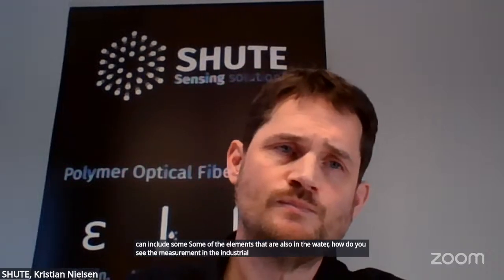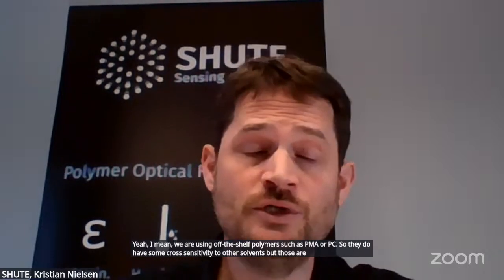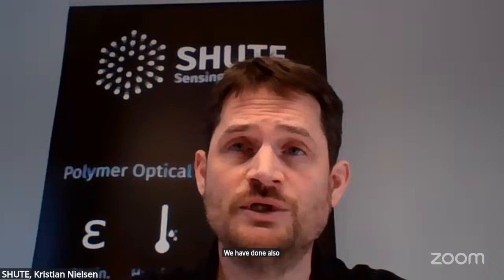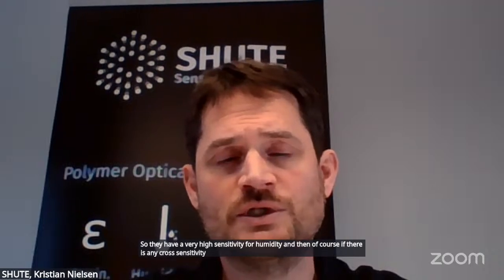And I have another question regarding the measurement of humidity. Is there any potential source of error with other liquids or other kinds of components that can include some of the elements that are also in the water? How do you see the measurement in the industrial pipes that you mentioned, for example? Yeah, we are using off-the-shelf polymers such as PMMA or PC. So they do have some cross sensitivity to other solvents, but an initial screening can be done by just looking at the polymer database to find out what exactly they're compatible with and not. We have also done tests for measuring moisture in different types of oils, and that's a very nice application for these kinds of sensors. So they have a very high sensitivity for humidity, and then of course, if there is any cross sensitivity with other liquids, that should of course be screened.